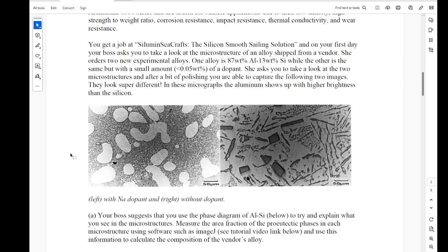Can we just use that scale to quantify the area? You don't actually need that scale bar at all. If you load this up in ImageJ, it's going to be an image that you upload. The image will have some number of pixels, so you know the total number of pixels. And what ImageJ lets you do is lasso them, and it will tell you how many pixels are inside the lassoed areas. Oh, so then you'll have the fraction. Yeah, the fraction of pixels inside versus outside will give you the area fraction of the circled regions, if you've gone through and carefully circled these things.